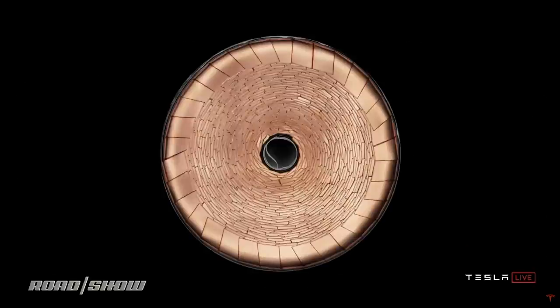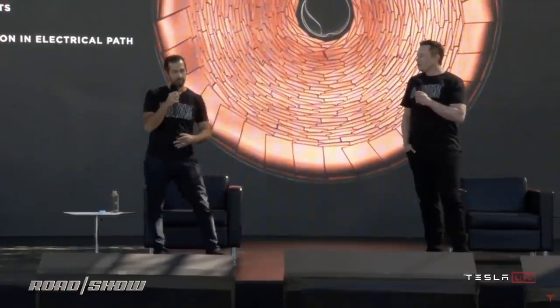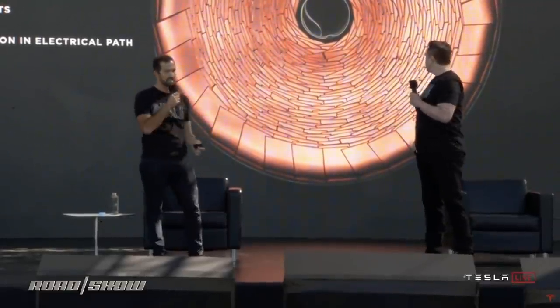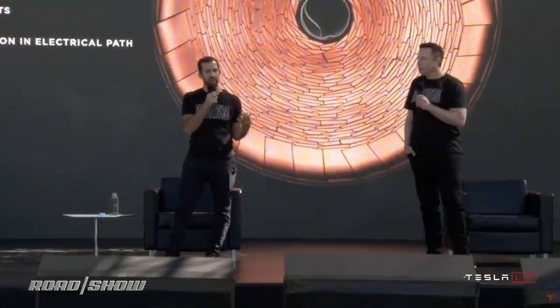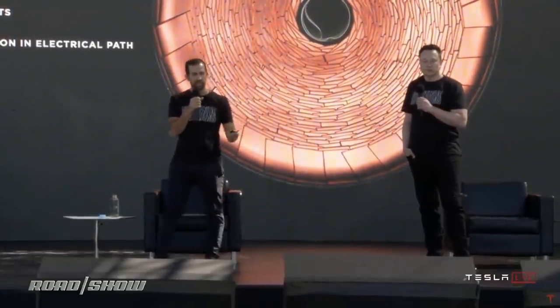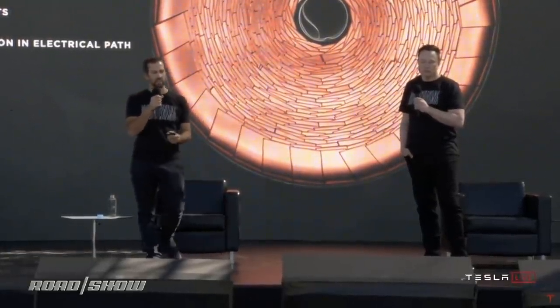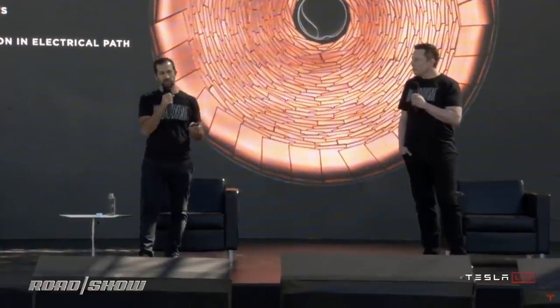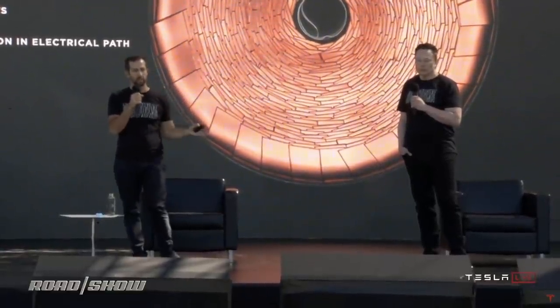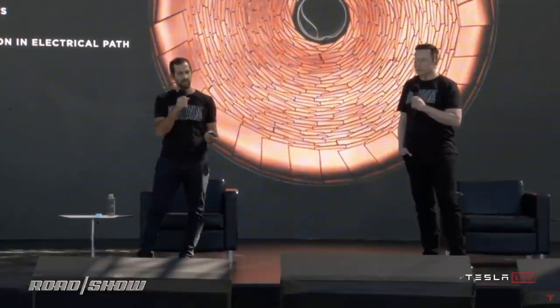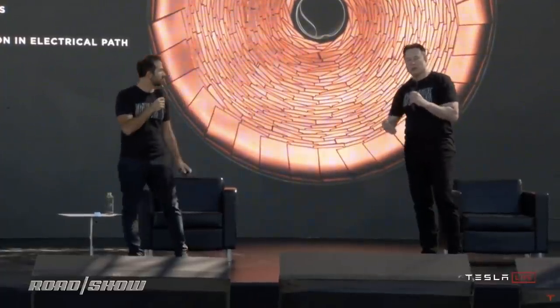And this is what we mean when we talk about tabless. It's kind of a beautiful thing. We basically took the existing foils, laser patterned them, and enabled dozens of connections into the active material through this shingled spiral you can see. With simpler manufacturing, fewer parts, 50 millimeter versus 250 millimeter electrical path length, which is how we get all the thermal benefits. Yeah, this is important to appreciate.